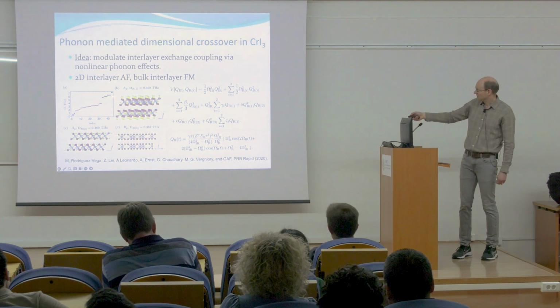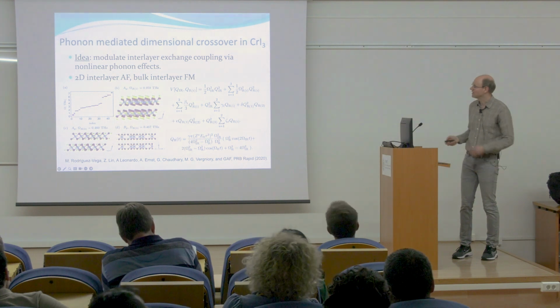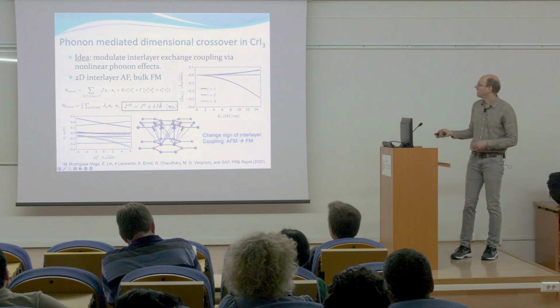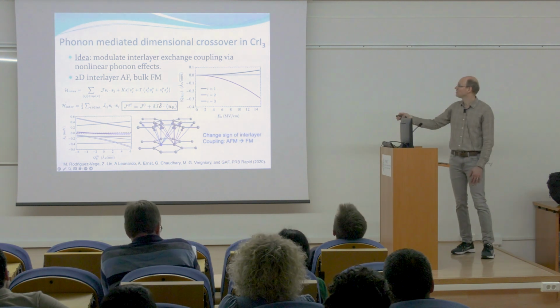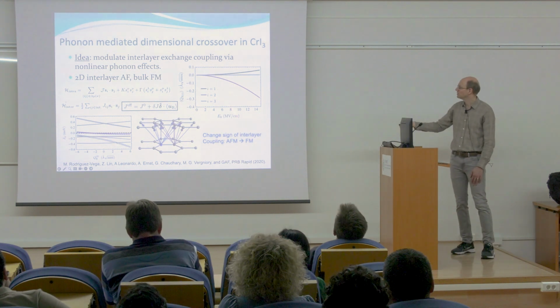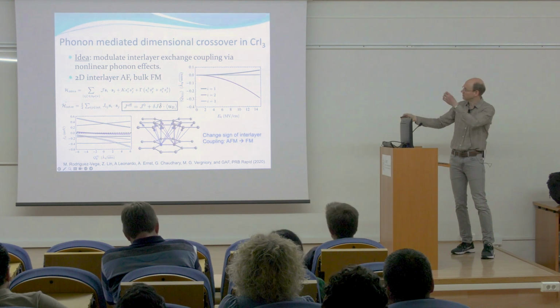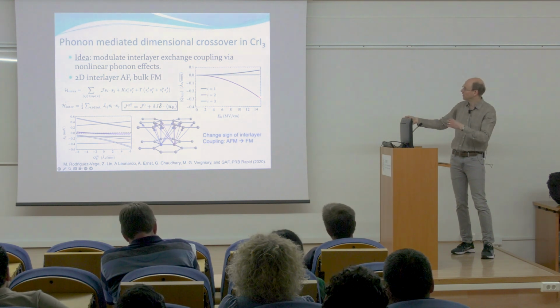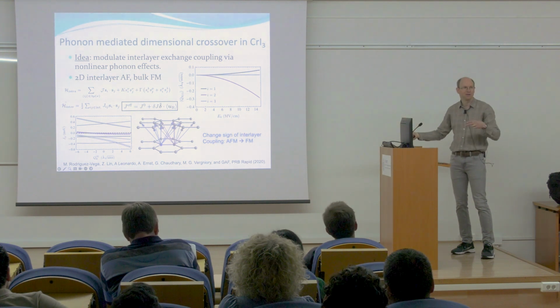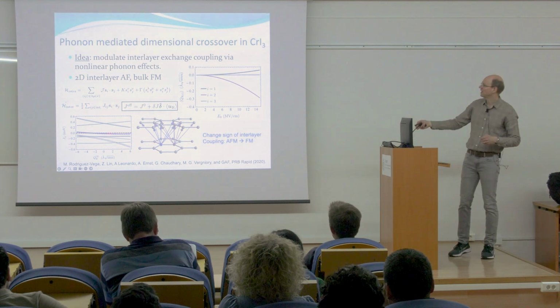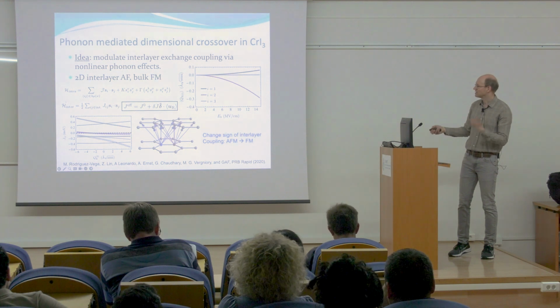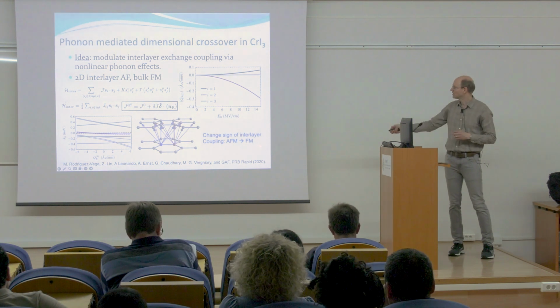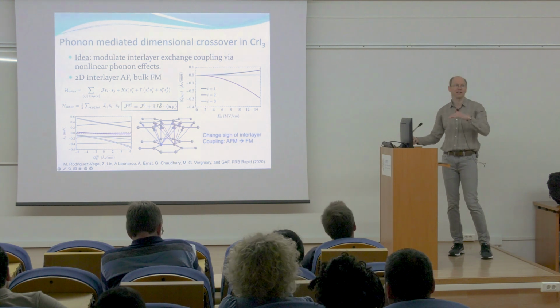So we want to choose the laser frequency to target the IR modes, and then we end up exciting certain Raman modes. The net effect that we find is that certain Raman modes respond with an amplitude, an amplitude of the shift in the equilibrium position, much more than others. So we can ask, how does this Raman mode change the symmetry of the crystal? And then calculate how the interlayer magnetic constants change. And we indeed can find a sign change. So we can change the material from antiferromagnetic to ferromagnetic with the light.